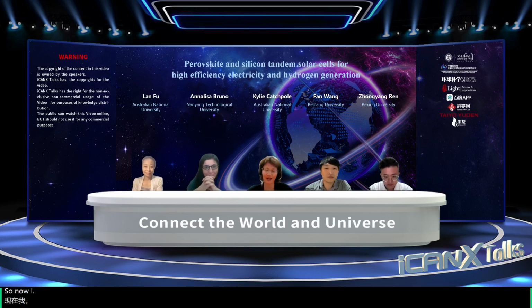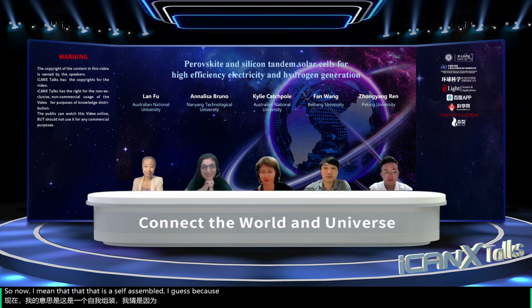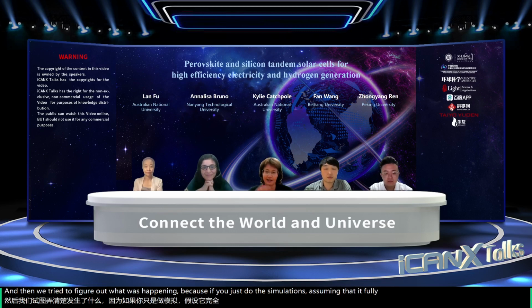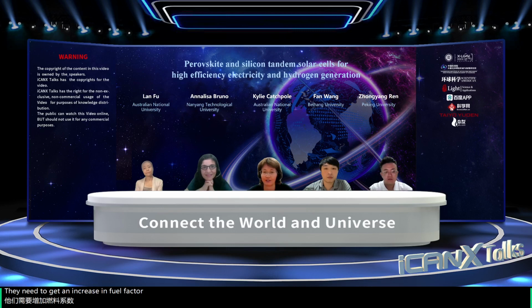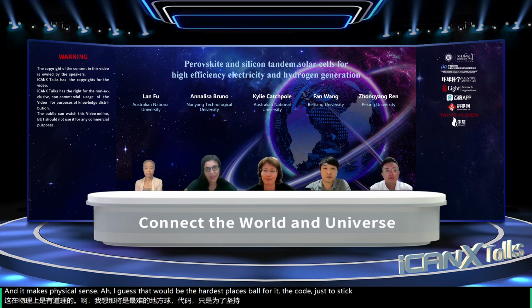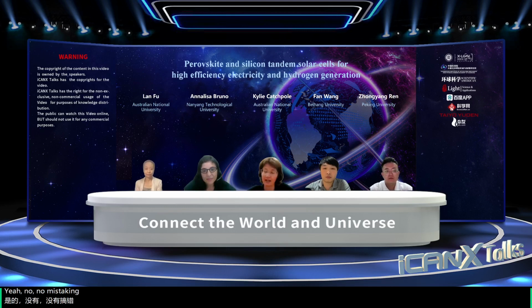Well, no, I mean that is self-assembled, I guess, because we spin coated the PMMA PCBM on top of the nanorods, and then we tried to figure out what was happening, because if you just do the simulations assuming that it's fully coated, then you don't get an increase in fill factor. So we were trying to figure out where the increase in fill factor could come from, and according to the simulations, the place it can come from is if the top of the nanorods is not coated, and that makes physical sense. I guess that would be the hardest place for it to coat. Just to stick. Yeah, the problem of sticking. But it wasn't controllable in the sense that we couldn't decide how much of the nanorods we would coat.